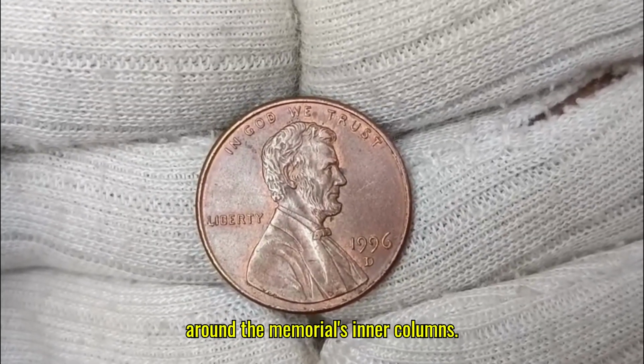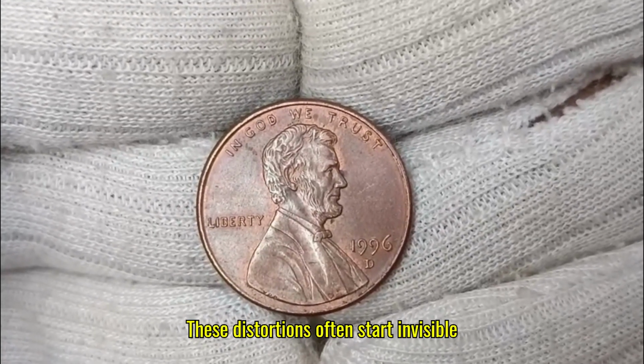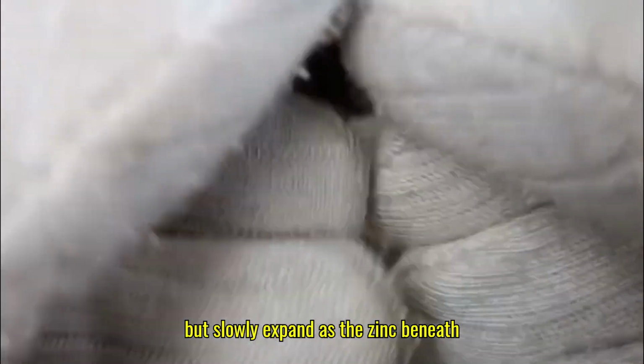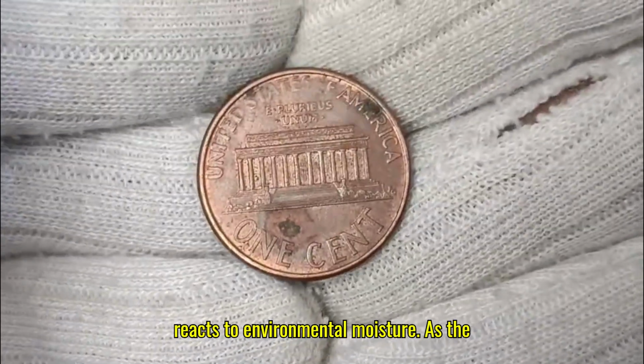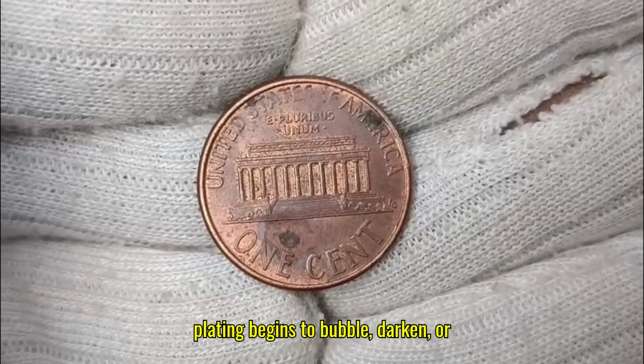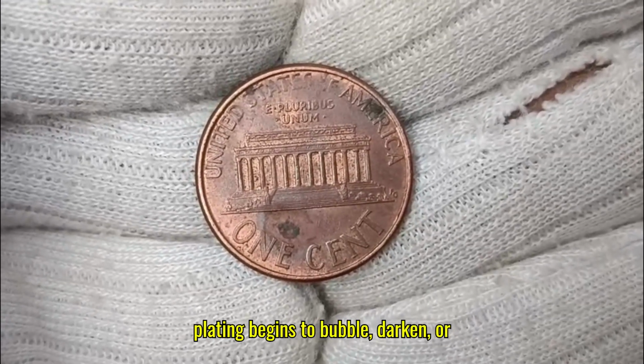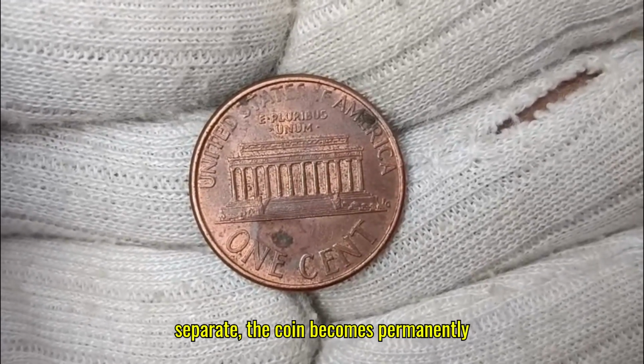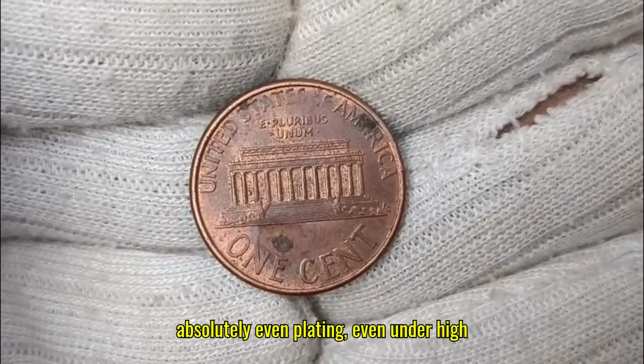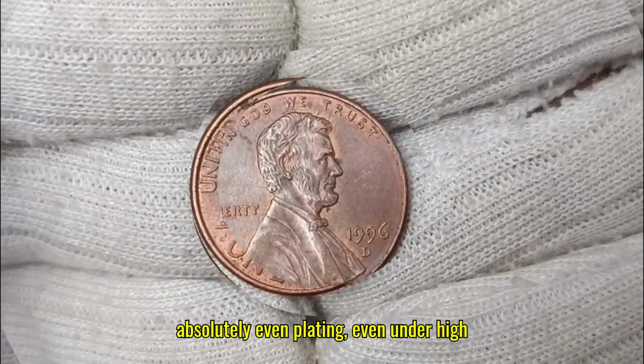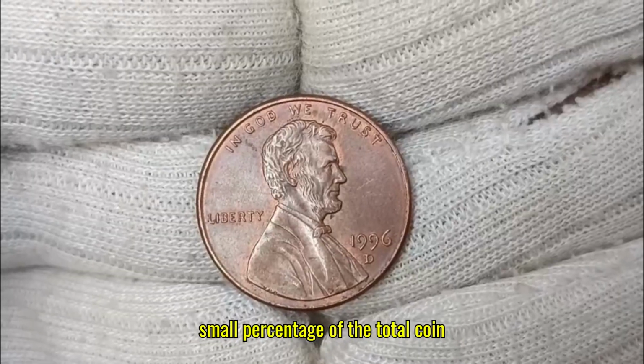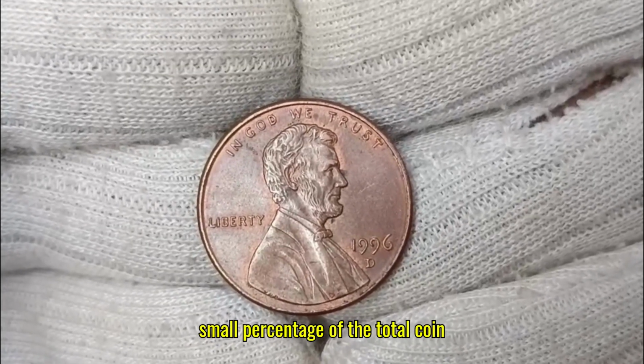the memorial's inner columns. These distortions often start invisible but slowly expand as the zinc beneath reacts to environmental moisture. As the plating begins to bubble, darken, or separate, the coin becomes permanently flawed. Surviving examples with absolutely even plating, even under high magnification, represent an extremely small percentage of the total coin struck.